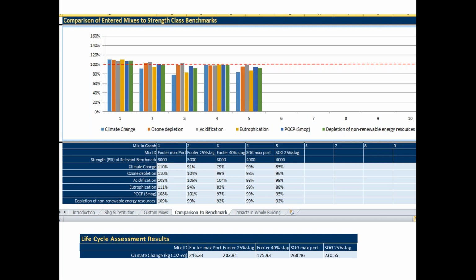We see this on this chart, and we can see that that first mix, if it had just had the straight Portland cement in it, obviously is going to be more than what the industry benchmark currently was back when they did the version 2. When we look at using that 25% slag, we can see there's a considerable drop. And from the climate change aspect, it's saying 91%. When we look at mix 3 with 40%, we're now down to 79%. For the floor work, we're seeing a 15% reduction. And these all come in handy as we get further into the LEED aspects of it, and I'll explain why later on. Next slide.